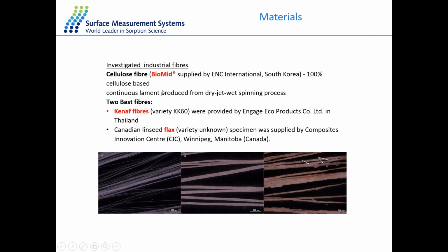So we have three different types of fibers. First, we have our industrial fiber. So this is a cellulose fiber called Biomid, and this is produced from a dry jet wet spinning process. So in this case, it's a processed cellulose fiber, and the other two we're looking at are natural fibers. So in this case, we're looking at the kenaf fiber and the flax fiber. So this is the resulting SEM images, and this is the Biomid, the kenaf, and the flax fiber.